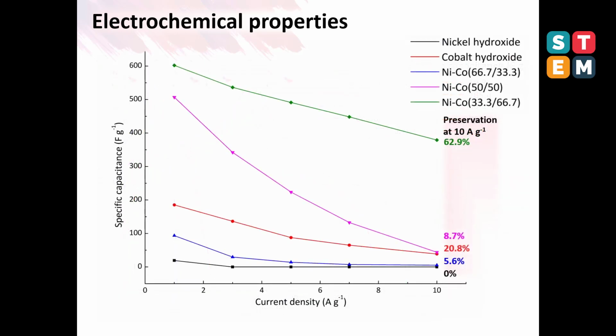When investigating the capacity retention at 10 amp per gram current density, the optimum ratio shows the highest retention at 62.9%. These results show the high efficiency of the electrode at high power.